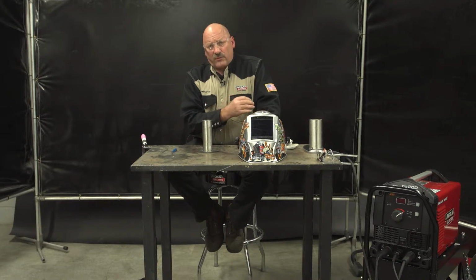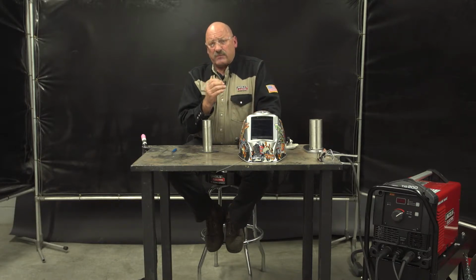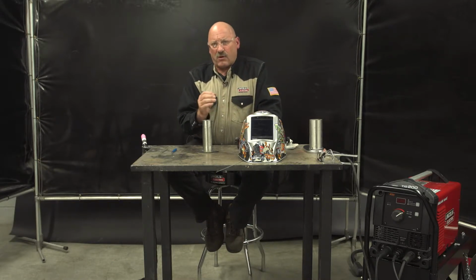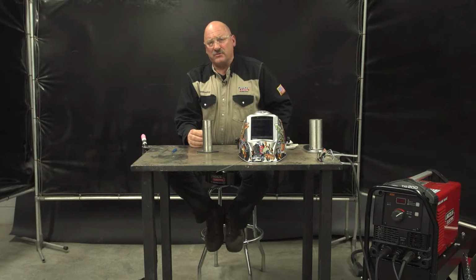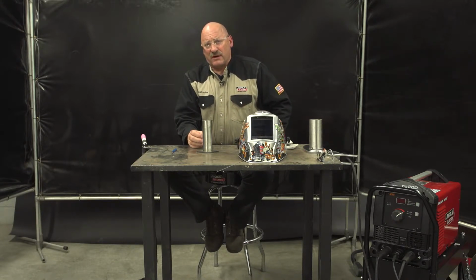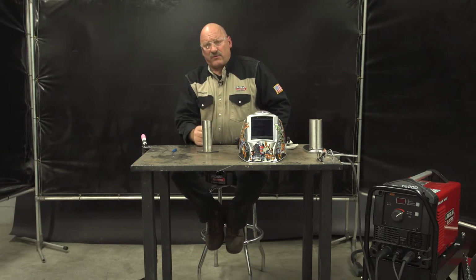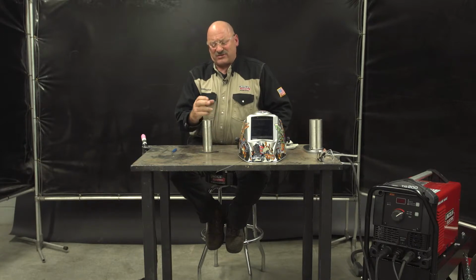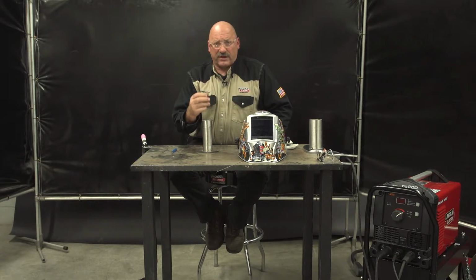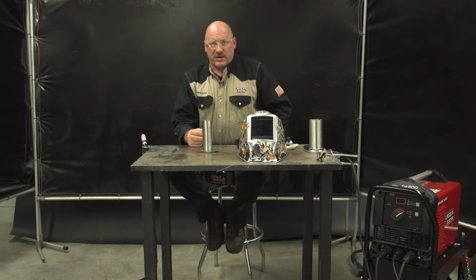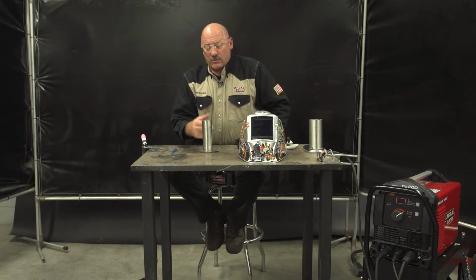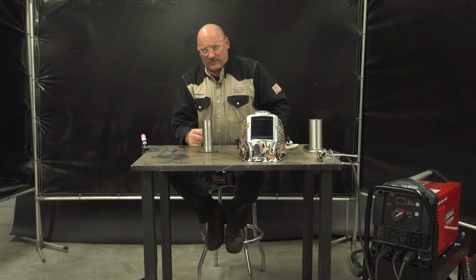310 stainless would work pretty well if that's what I had, but we have to be careful about solidification cracking. There's absolutely zero ferrite in the weld, and sometimes phosphorus, sulfur, and other things that get into the steel can lead to solidification cracks on stainless steels that are fully austenitic. The 309 stainless has just enough ferrite in it to prevent solidification cracking, but not so much ferrite that it will develop a brittle microstructure at extended service temperatures above 800 degrees. So we're going to choose a 309 stainless for the filler metal today.